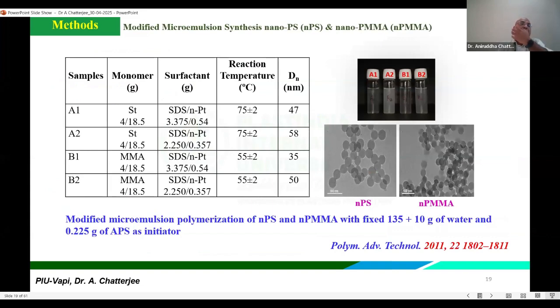So this is about the modified microemulsion synthesis process. Here I have synthesized polystyrene as well as polymethyl methacrylate nanoparticles with the help of modified microemulsion process, where sodium dodecyl sulfate is used as a surfactant, and ammonium persulfate as an initiator over here. This A1, A2 is related to styrene nanoparticles, and B1, B2 is related to polymethyl methacrylate nanoparticles.